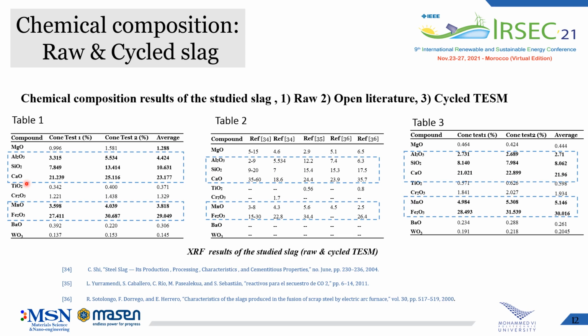The XRF analysis shows the chemical composition of the slag material in the first table. The major compounds are aluminium, silicon, calcium, and iron in the form of oxides. This composition is in good agreement with the similar slag material reported by the literature from other industries. After thermal cycling of the slag material, we have a slight variation of the chemical composition, and thus due to the oxidation of wustite.